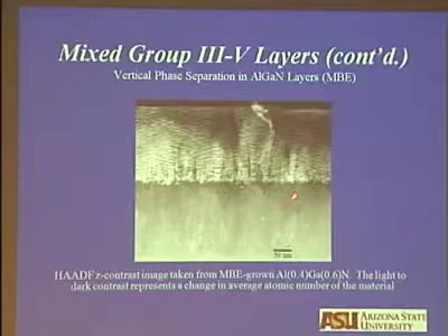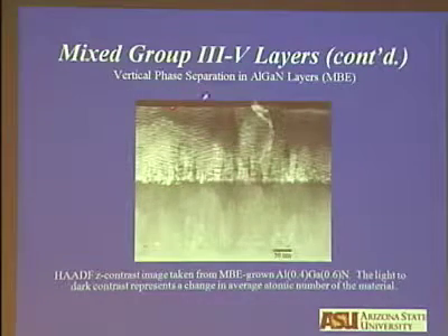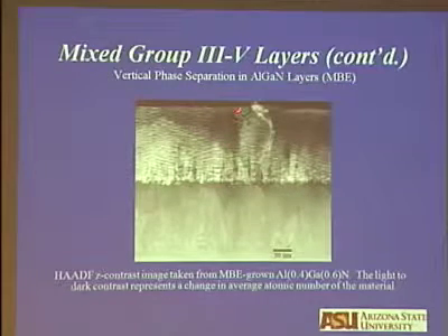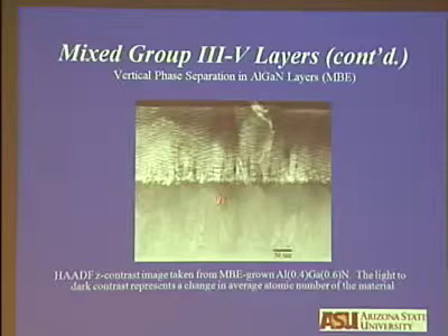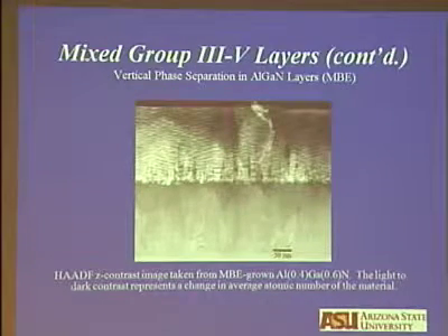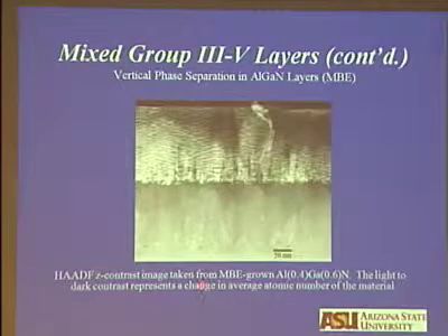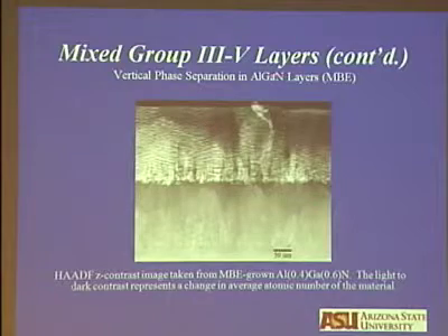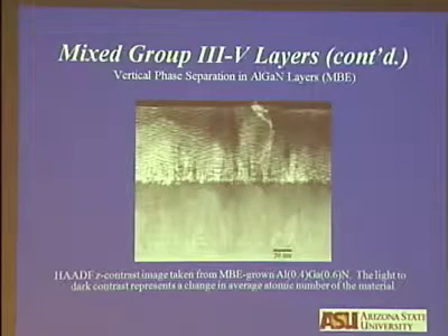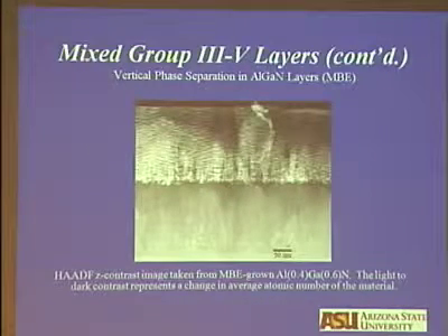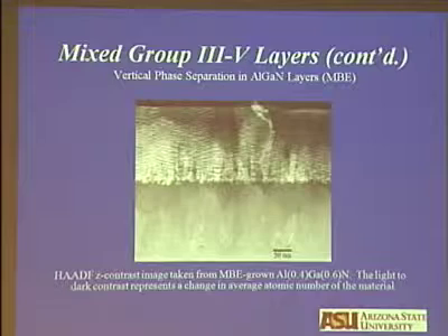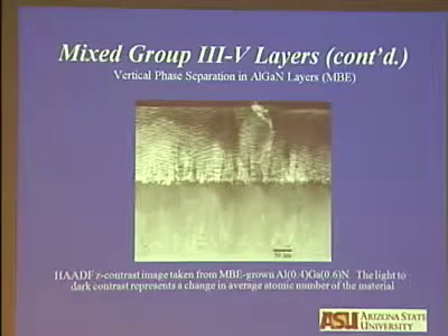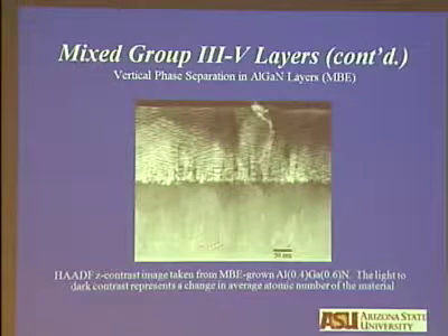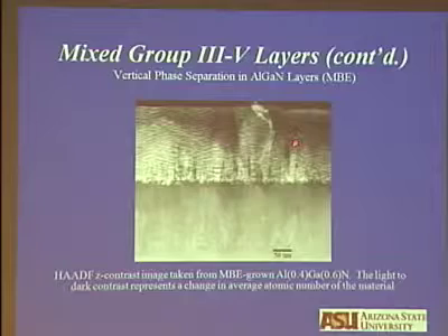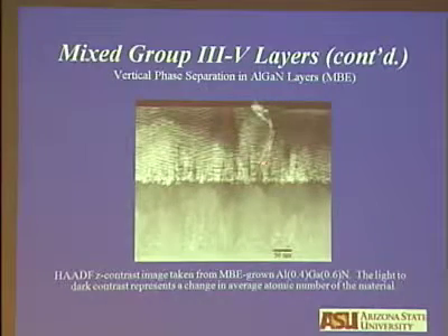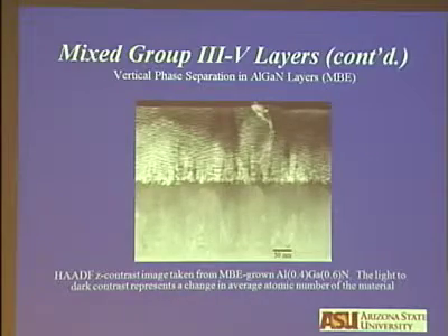This is the structure we were not trying to grow, but we were trying to study phase separation in aluminum gallium nitride. And what you get is a vertical alignment of the phase separation, vertical modulations. The light region is the gallium rich, and the dark regions are the aluminum rich. And they line up in the vertical direction. We were puzzled why this happens in these materials. I will give you an explanation of why this happens. By manipulating the growth conditions, I would be able to change the period along these directions, and the extent of these modulations is shown here.